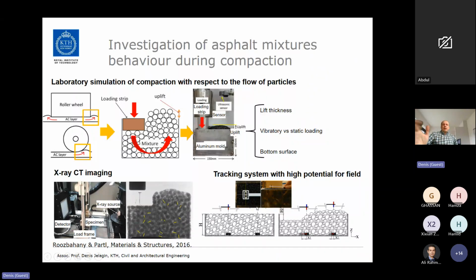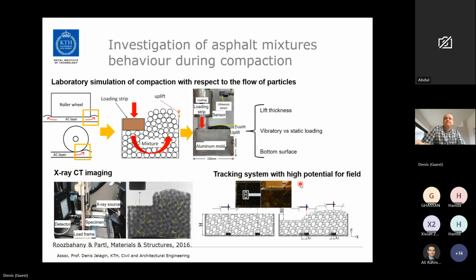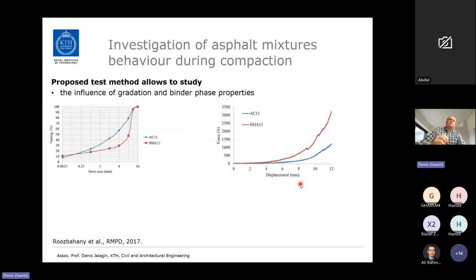And finally, not every test can be performed inside computer tomography system. So at the end of PhD project, we also tried to develop tracking system to be used in the field or in the lab, but without necessarily need of using computer tomography system. So this test method was able to differentiate between the effect of different parameters on asphalt compactabilities. So we looked at the effect of RAP, gradation and binder phase properties.